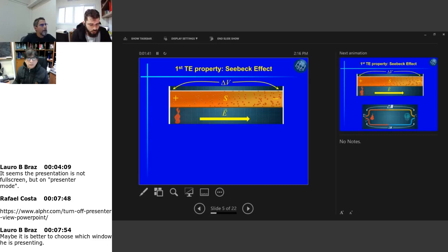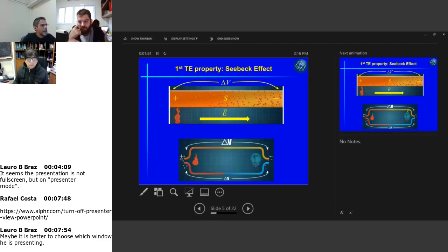So the property that measures how strong this difference of potential can be is called the Seebeck coefficient, which is also known as the thermopower. How can you generate a current with this effect? If you have two different materials, the top one and the bottom one here, with different Seebeck coefficients, the Seebeck coefficient here is higher than here, then the difference of potential here will be larger than here, although they are both in the same direction. So the current here will be larger than the current here, so you're going to have a net current generated around this loop.